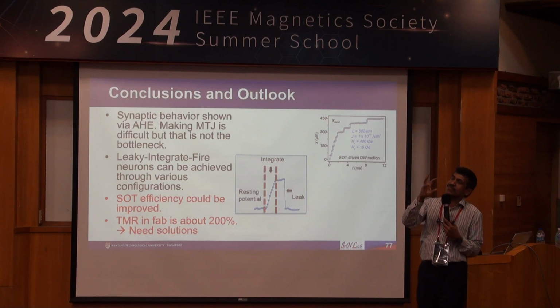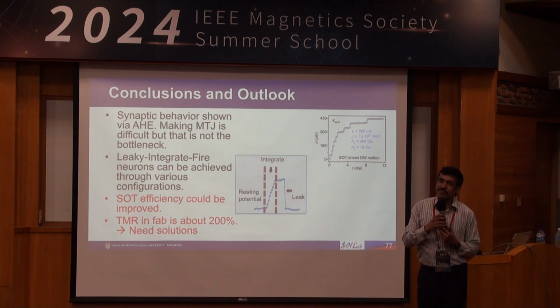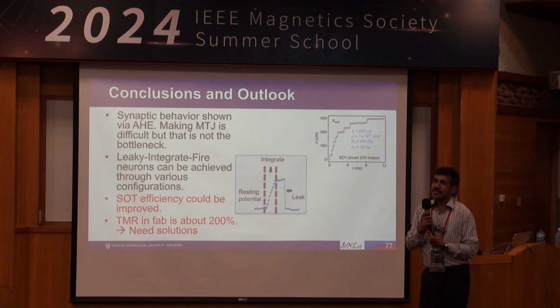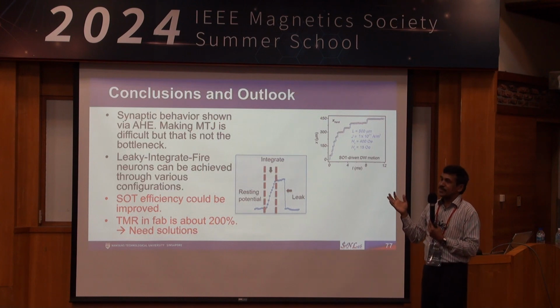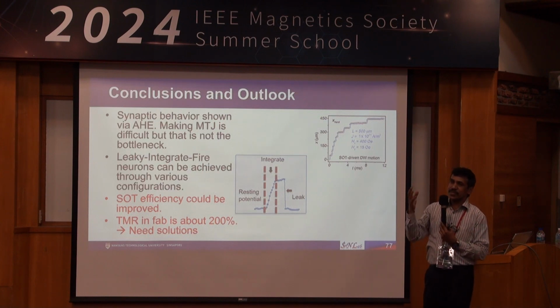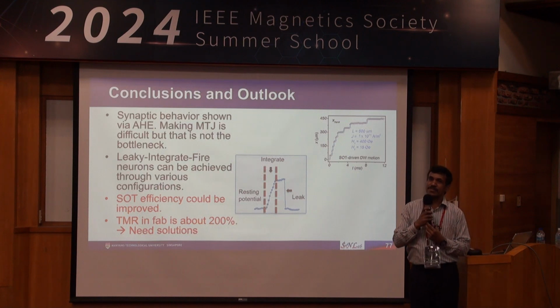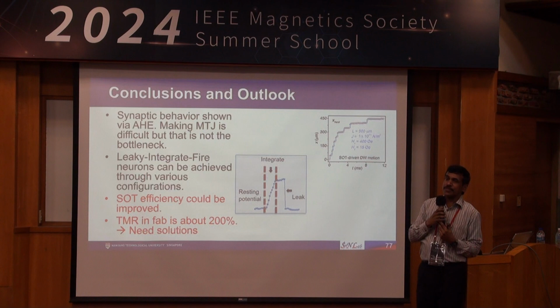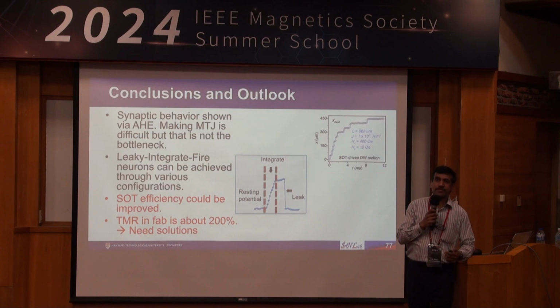After 10 power 5 cycles, the device will be useless. The device will not produce reproducible results. But the endurance of spintronic materials is much larger, about 10 power 15. So it's like 10 orders higher than the phase change materials. So in that sense, these materials are superior. Okay, thank you.